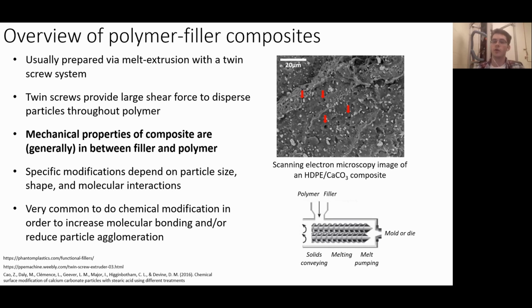So we've got an image of one of these composites up here on the right. This is an SEM image of a polyethylene and calcium carbonate composite. We can see there's actually a pretty good dispersion of the calcium carbonate particles. However, there is a very large size distribution, which means that we're seeing some sort of agglomeration here, which is interesting, and I'll talk about this a little bit later as well.